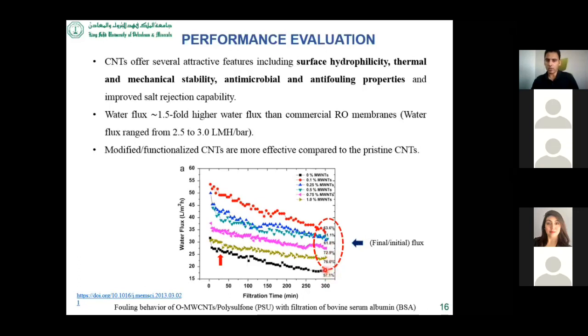Okay, so this is very low in case of the membrane without the carbon nanotube. But if you add carbon nanotube, this ratio is increased. This means that less fouling occurs. Of course, there are some other details. I will not go into them at this stage. You need to optimize the dosage of the carbon nanotubes, because if you add a large amount of the carbon nanotube, some agglomeration might occur. And due to this agglomeration, the properties will be reduced again. So you need to define that optimum dosage basically.